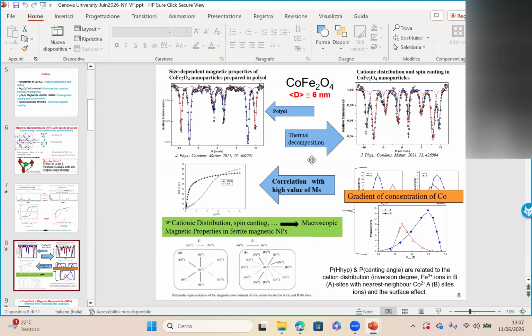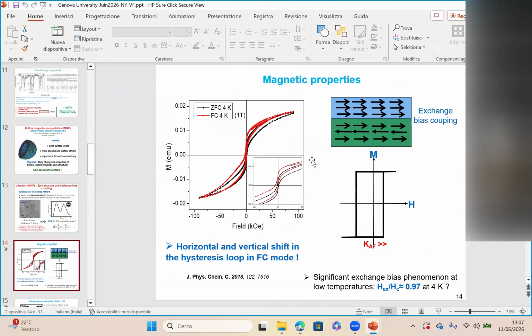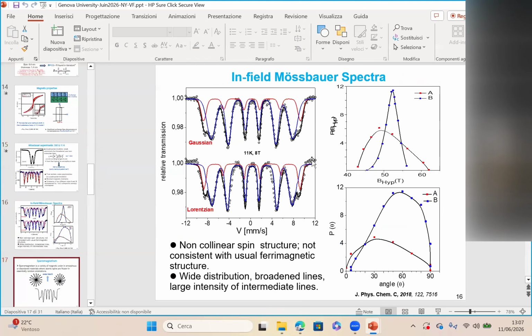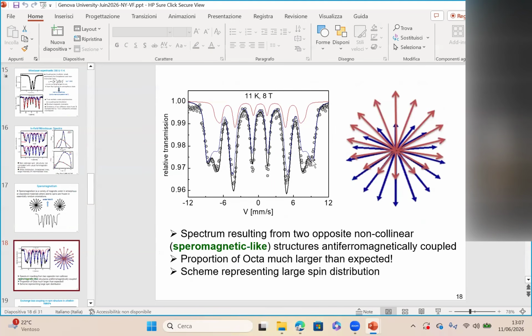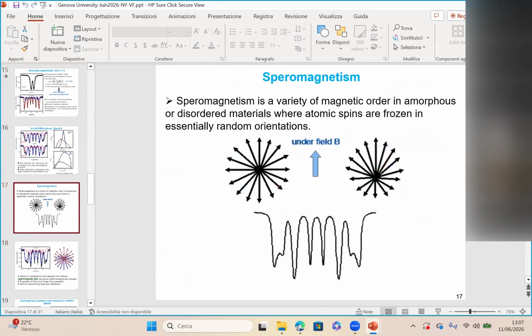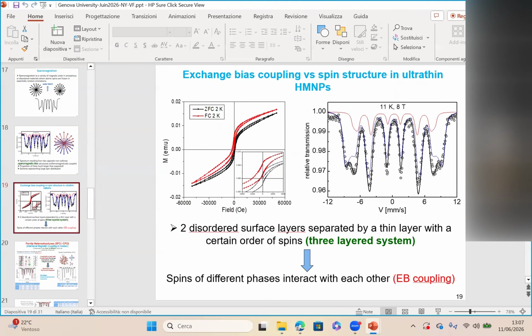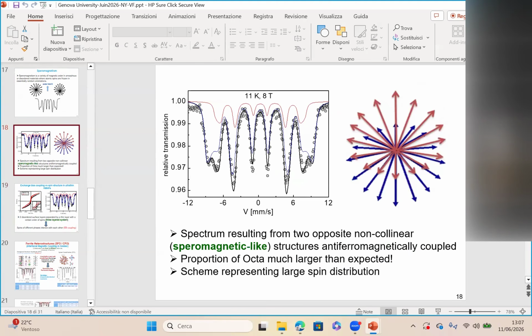And what I also wanted to add is with respect to the hollow nanoparticles. 25 years ago we were discussing with Jean-Louis, with Dino, and with Elisabeth Tron what could be the surface of nanoparticles, especially of maghemite. And we came to the conclusion that probably there are many more octahedral units than tetrahedral units. But we did not have any argument. It was only an assumption. Why not? But now, thanks to these measurements on hollow particles, we are quite sure that at the surface there are many more octahedral units to close the structure than tetrahedral units. 25 years after. Thank you so much.